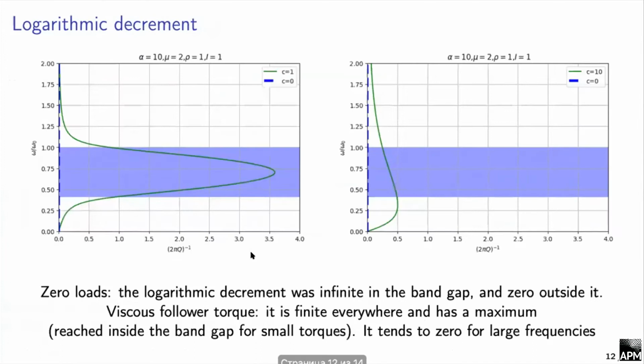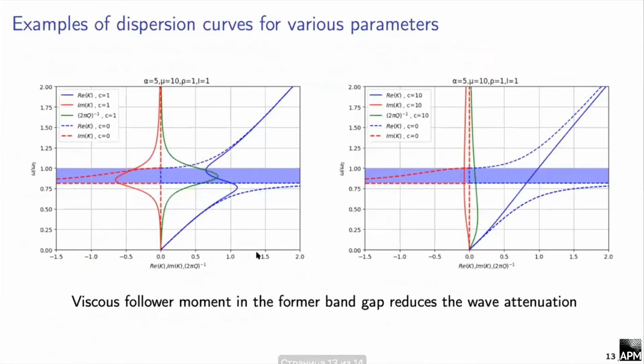So, in conclusion, I would like to tell that comparing our results with the case of zero external influence, it can be noted that a positive elastic following moment increases the speed of the shear waves at a low frequency and pushes the band gap to the region of higher frequencies. A viscous following moment completely destroys the band gap, while with very high viscosity, a falling section of the dispersion curve will appear.